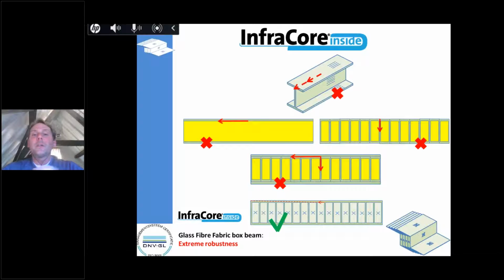What you see here are typical composite approaches. On the upper left, you see a classic sandwich structure consisting of two facings with in the middle a structural core. And this red arrow is showing that if a crack would propagate between the layers, it would just continue to grow and grow. On the upper right, you see a typical pultruded box assembly. This approach has been extensively applied in the US, for instance, in bridge building, and all these bridge-like structures have failed in a couple of years. So again, the red arrow is showing that if a crack starts to propagate between these pultruded beam profiles, it can just continue growing.